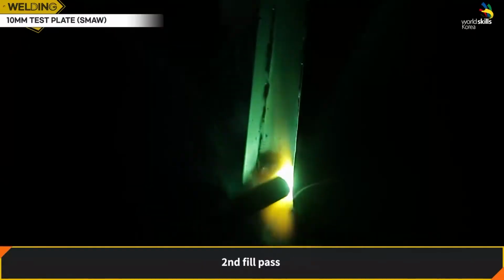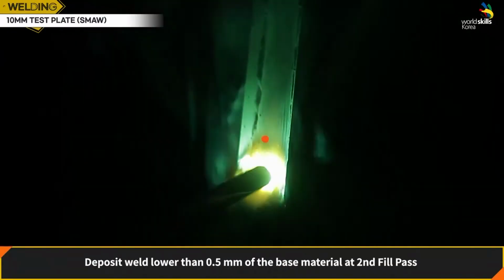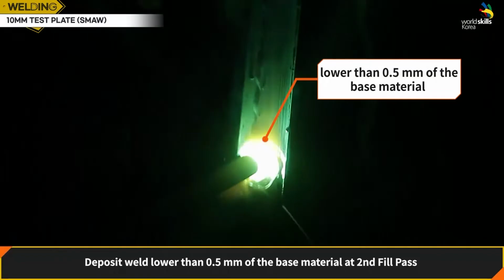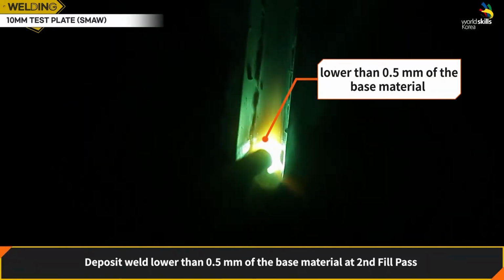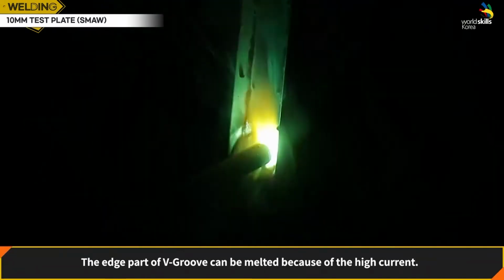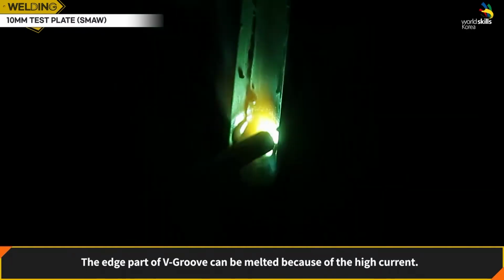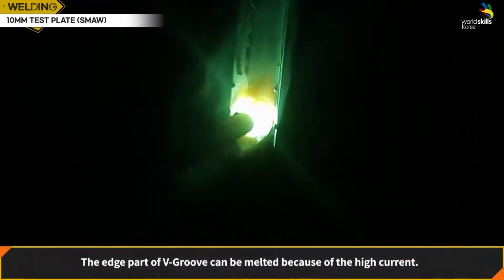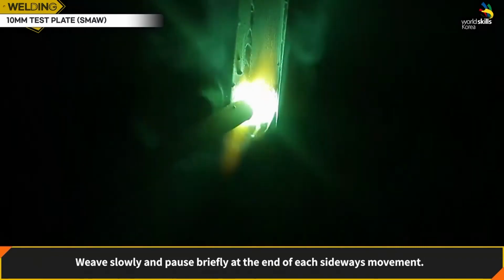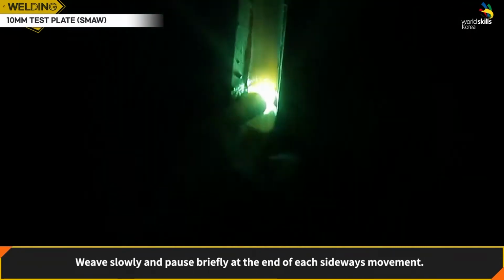Base material. Second fill pass. Deposit weld lower than 0.5 millimeters of the base material at the second fill pass. The edge part of the V-groove can be melted because of the high current. Weave slowly and pause briefly at the end of each sideways movement.